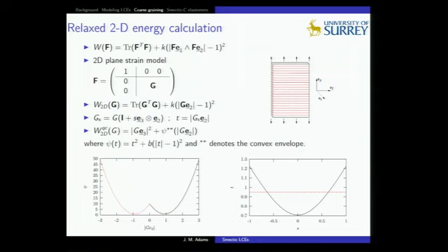And what's nice about this is for a simplified energy, and if you take a two-dimensional example, you can show explicitly how to make its relaxed energy just by considering rank 1 connected deformations. So this is the free energy that I wrote down on the previous slide, and I've written out the cofactor explicitly in terms of the cross product of two vectors in the initial plane, E1 and E2, and then deform those with F. So that's just what the cofactor is doing.